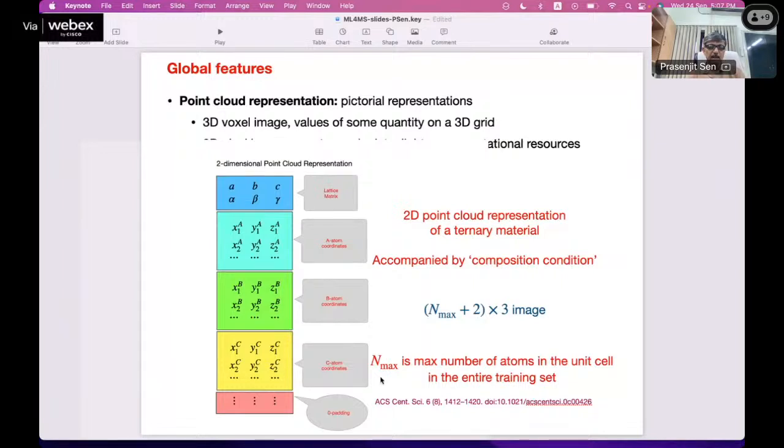And so the last block: you have given the lattice structure and the positions of the atoms in the unit cell, but you need something more, which ideally is the chemical properties of the elements that we have discussed before. In this particular representation they did not give chemical information in this last block, but in the subsequent ones this was used.